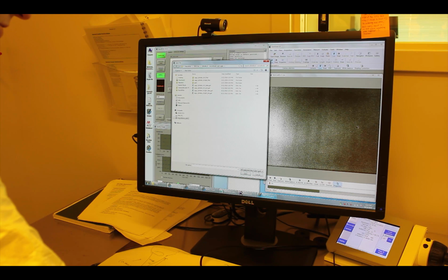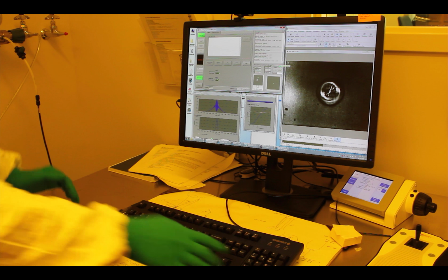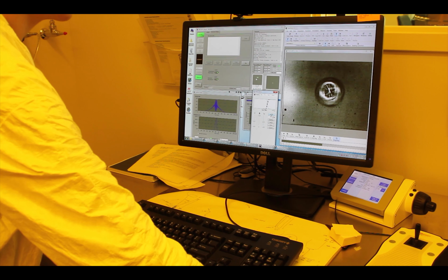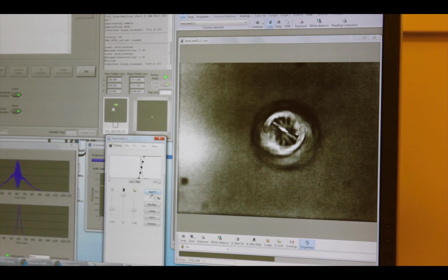Once we have our laser calibrated, we can start the job, and you can see a live view image of what's printing as it steps up through the Z height using the piezo stage. And the whole process is extremely quick. So for this 300 micron tall structure with resolution around half a micron, we can print this in about 30 seconds. So here's our final structure.